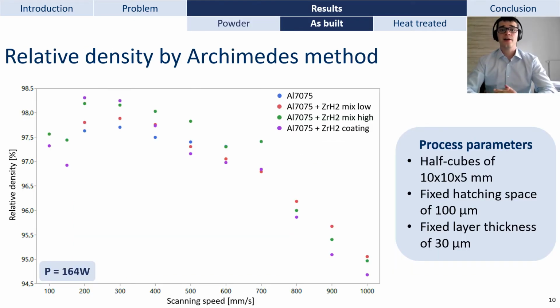Now that the powder has been thoroughly analyzed, let's look at the LPBF optimization process. We will look at the relative density obtained by the Archimedes method for cubes of 10 millimeter size, processed with a fixed hatching space of 100 microns and a fixed layer thickness of 30 microns. We have tested a lot of different combinations of laser power and scanning speed, and we found that the low laser power of 164 watts gave the best density results.